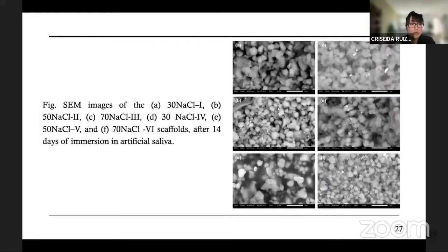Then it continues with scaffolds that were evaluated in vitro using artificial saliva, to be used in dental applications. The hydroxyapatite precipitation occurred after 14 days of immersion in artificial saliva.